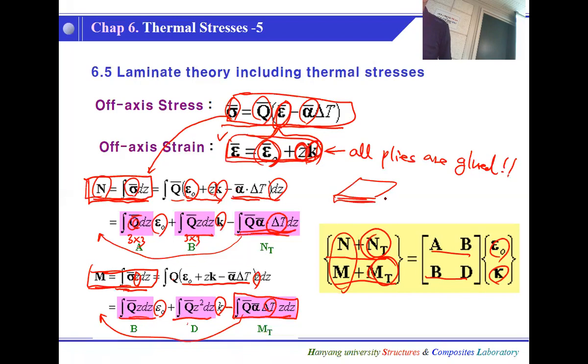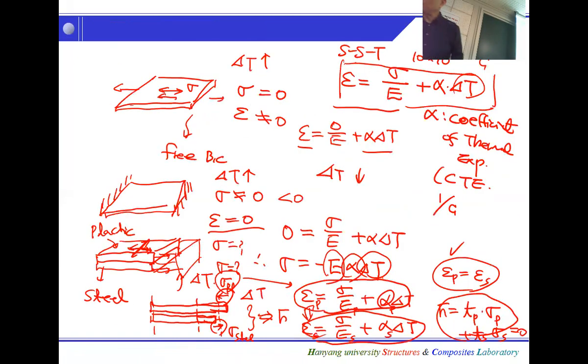So these are the external loads we are applying. We have lots of layers, and we have N and moment. Now we apply delta T. This guy would cause these terms. Where are they located? It looks the same as the external load. So imagine even though we don't apply any load, the delta T will act as an external load, which would cause the epsilon 0 and curvature. So let's say we have a plate with a layup sequence, increase temperature, it will extend and bend. And conceptually, as you can see here, Q alpha delta T. Q is stiffness, alpha is CTE, delta T. That's exactly the same as what we observed here.